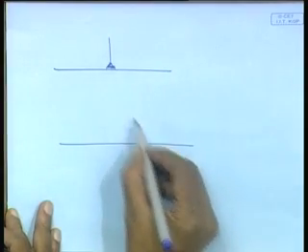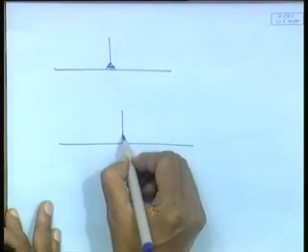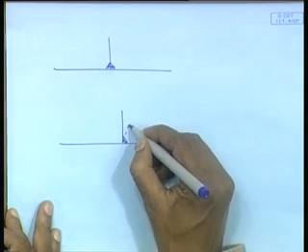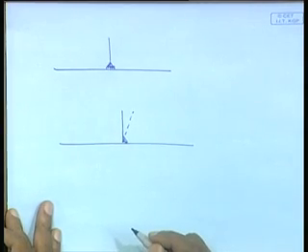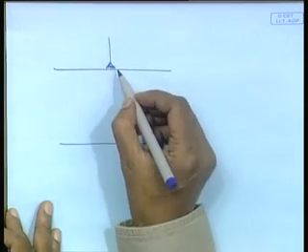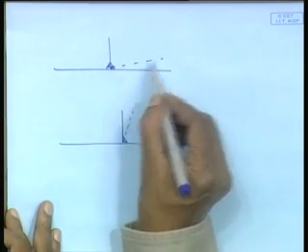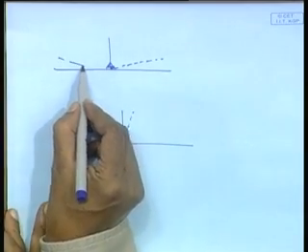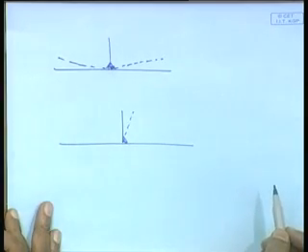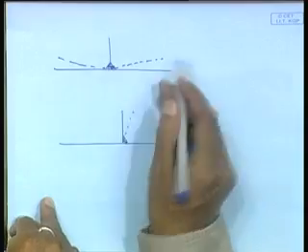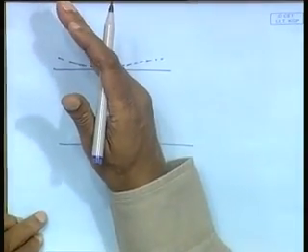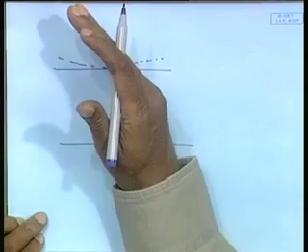one, say a plate is there, a vertical stiffener, you weld one side, it may lead to the stiffener getting deflected like this, or the stiffener is vertical and the plate is deflecting like this, on both sides. When this side is welded, this lifts up, when this side is welded, the other side lifts up. That is what is angular deformation.